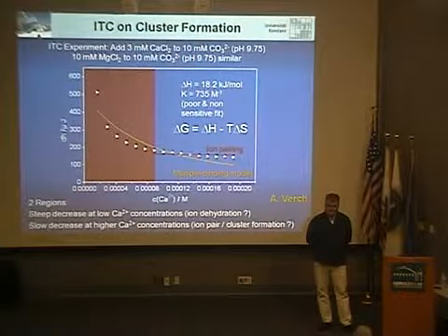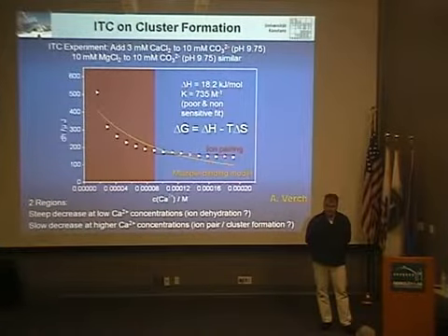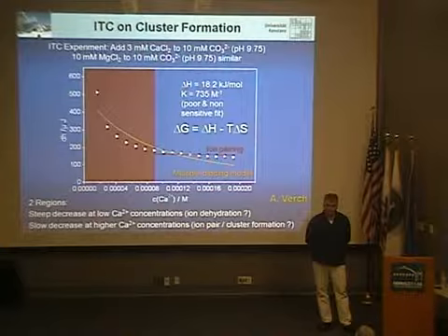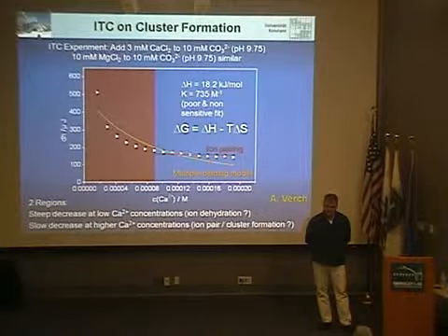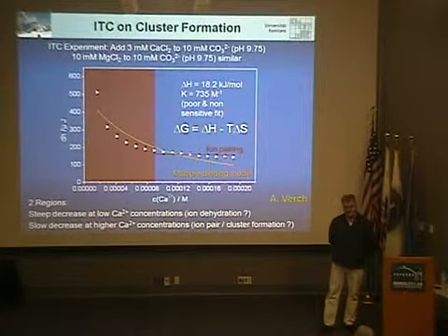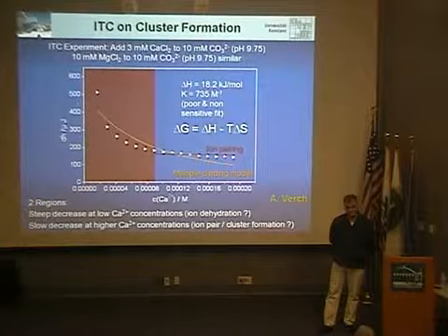So doesn't this actually constitute the basic explanation as to why you see no more than, say, 18–20% Mg substitution in biogenic calcites, and that you're not likely to ever see magnesium carbonate as a predominant component, because you're never going to get beyond nesquehonite or lansfordite or these hydrated magnesium carbonates.